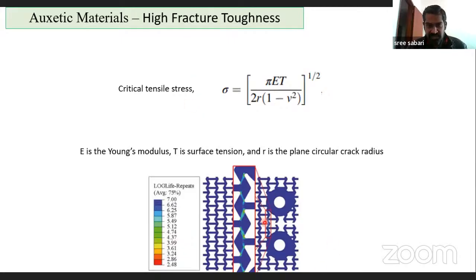So in this figure, you can see a schematic diagram showing the fracture toughness test. Here you can see this is the initial crack used for the testing, and these are the two fixture regions, and it will be opened. So here a loading condition fixture is there, so it can be opened. On magnifying, you can see that these are the potential regions where the crack can initiate. But in order to initiate the crack, you need to apply more energy to create a crack here.